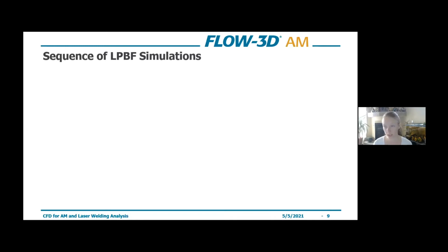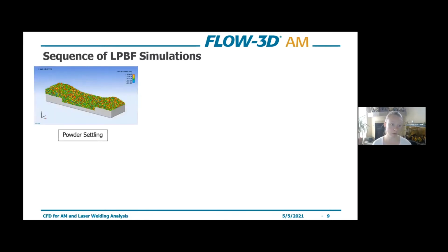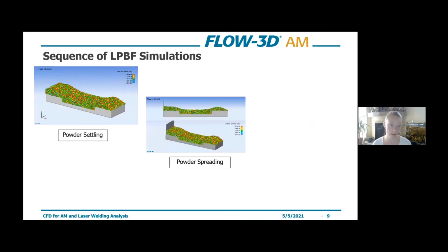So to give you an idea of how this breaks down, for laser powder bed fusion, when we go through this modeling workflow, we start with powder settling and spreading. So we account for the powder distribution, any sort of cohesive, adhesive effects within the powder, maybe due to moisture or electrostatic forces. And ultimately what we're trying to get is that final powder compaction in the powder layer that we can then perform the melting simulations on.